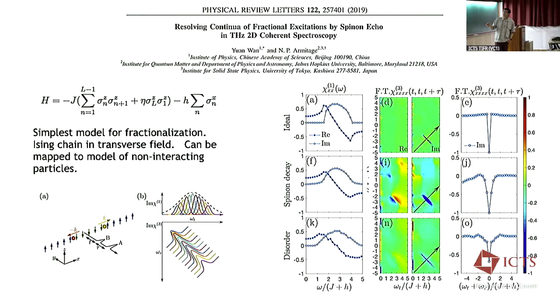And so we did a series of calculations that were associated with this. This is the linear response here. This kind of broad shape is an ensemble of many different possible excitations that correspond to making two of these domain walls traveling apart from each other. There's no particular sharp spectroscopic information that can be extracted from that, again, because the excited state is a two-particle continua. But along, and here in the fourth quadrant, you see this kind of sharp streak, which is this sheet